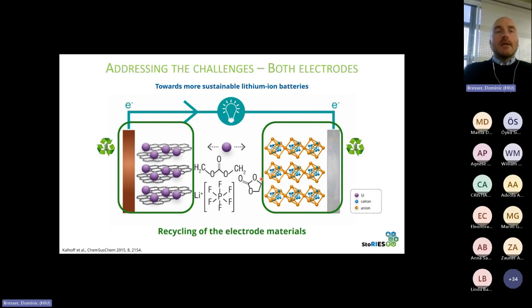Mentioned earlier, right, recycling is another way apparently to potentially improve sustainability of batteries. And this apparently can be done for all the components. I mean, the recycling of the current collector, copper at the negative electrode, aluminum at the positive electrode is relatively simple, I may say. But if you have a lithium transition metal oxide like nickel, cobalt, manganese oxide, it's a bit more difficult also already to recover the different elements. And we're talking about graphite. It's apparently an issue as well because any kind of high temperature treatment under oxygen, right, would just burn off all the graphite.